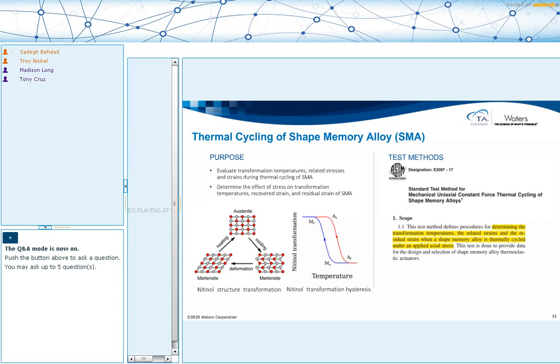And if you start from room temperature, so in the little schematic that you see on the left, the hysteresis loop, if you start from room temperature and start heating up your sample, so follow the red line, you will have a temperature where your austenite starts to form, and then it takes a few degrees until this transformation is completed. And then as you cool it back down, you start to form the martensite phase again, and you will be fully martensite if you are cooled all the way down below that temperature.